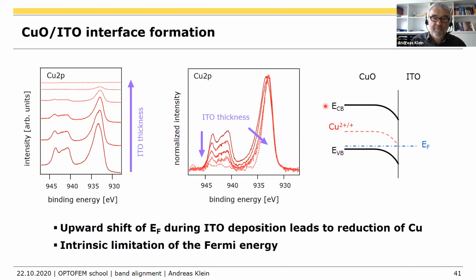You want to make copper oxide, a perfect material for solar cells. 1.5 eV band gap, it's a dream. Very simple to make, very cheap material, very abundant material. A dream to make, but it doesn't work. And probably a main reason for this is that you cannot go with the Fermi level up here. There's no way, because copper monoxide is not stable with the Fermi level here, because if you raise the Fermi level, you reduce the copper.